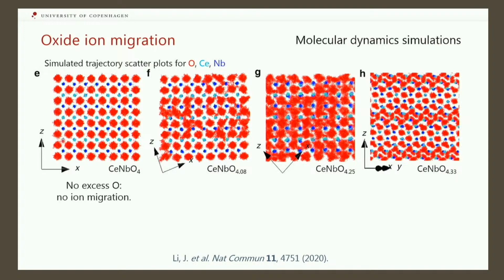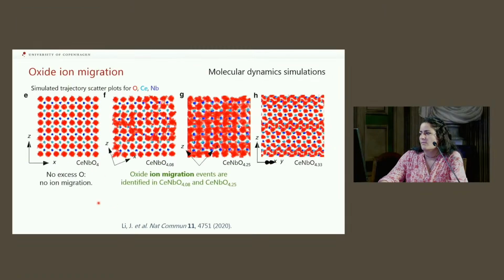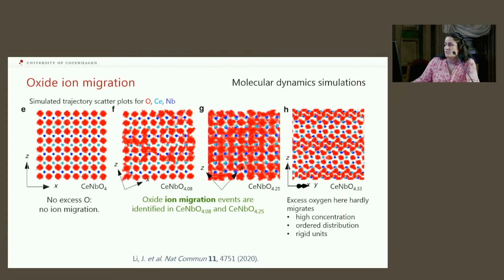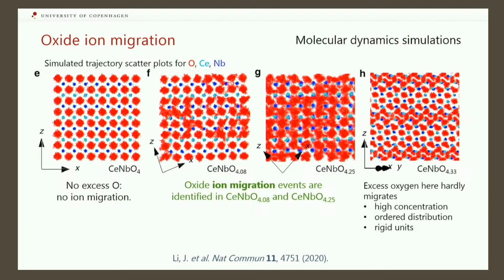So we have no migration in the case when we don't have any extra oxygen, any interstitial oxygen. But it's very clear in these 2 intermediate phases. And on the other hand, we have almost no migration also in the oxygen-rich phase, because for the interstitial oxygen to migrate, it needs to find empty positions nearby, and when there is too much oxygen, there are too few empty positions. And also the structure here is more rigid, so no migration.